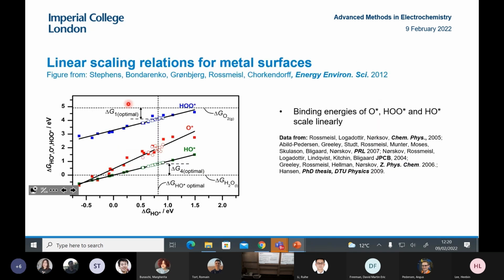It turns out, as it happens, they all bind. These intermediates, the binding energies of all of them scale linearly with each other, especially if you look at, for example, OOH binding as a function of OH binding. There's a really linear correlation. There's also quite a good correlation between the oxygen binding and OH binding. So this constrains the reaction. It means that you can't change the binding energy of the intermediates independently.